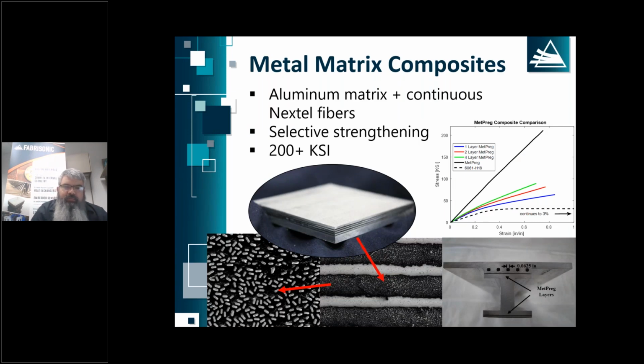This is another example of metal matrix composites. In an earlier example, I showed some fibers that were on the order of about 80 thousandths of an inch. These fibers here are more on the micron range, 5 to 10 micron fibers. Again, the little white dots at the bottom, those are actually continuous alumina fibers, so Nextel fibers. And we've embedded those in aluminum matrix. And you can see we have varying planes of this material, and those are oriented in different directions. And just like any other composites, metal matrix composites built this way follow the rule of mixtures. So we can easily calculate